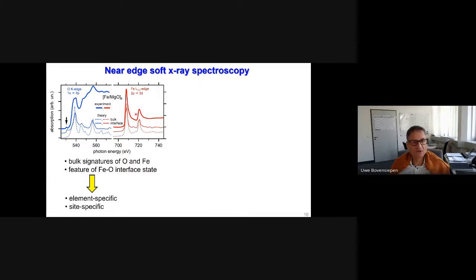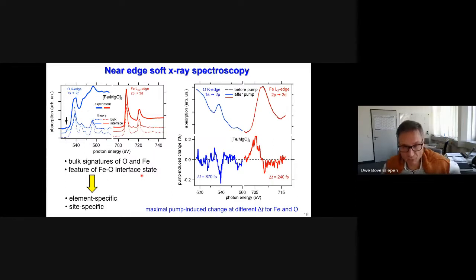At iron, we see the L3 and L2 edge. This matches very well with the calculations for bulk and interface. There's a small interface contribution that cannot be resolved since it's here in the white line. So we have here bulk signatures of oxygen and iron that also with this interface signature allow us element-specific and in particular site-specific analysis in our heterostructure. Now, let's go pump probe. So what you see here in the top, this is the absorption at the oxygen K and the iron L3 edge before and after pumping.